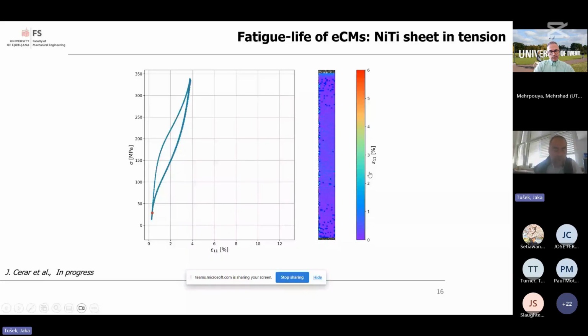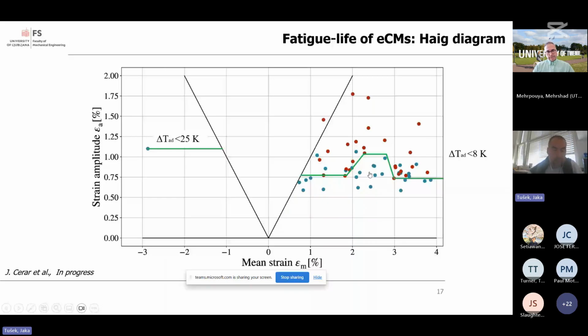So based on these results, we are currently constructing a Haigh diagram as shown here. The left-hand side shows pure compression, while the right-hand side shows pure tension. And this plot shows the samples that survived in gray and that failed in red. So they didn't reach 1 million cycles.